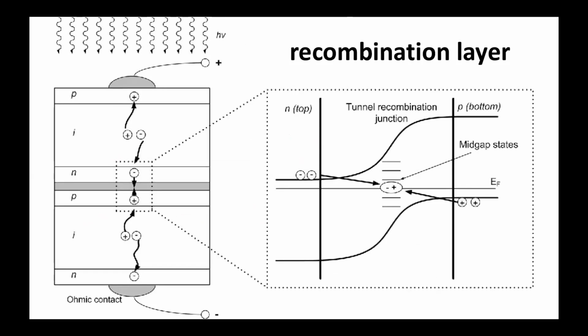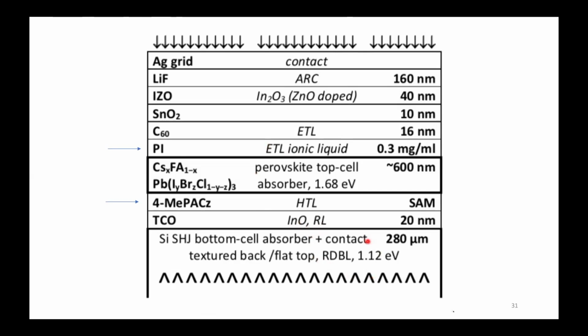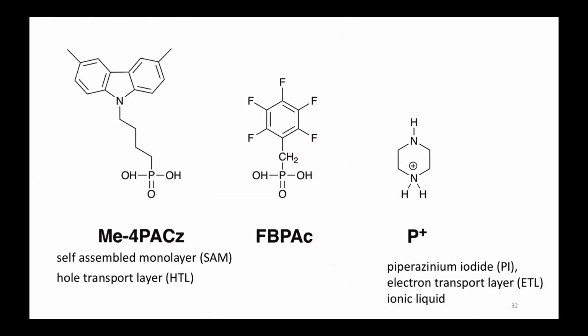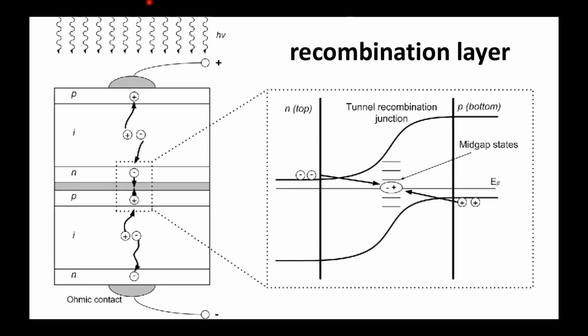One more thing, that is the recombination layer. Here we have the silicon, here we have the perovskite. In between, we also have a recombination layer. What does that do? It's 20 nanometer thick, and this is what it does. Here's the light. Here we have the top cell. With light, we create charges. We create an electron hole pair, a plus and a minus. But in the bottom cell, we do the same. So we also create a plus and a minus. Negative charges, they go one way.